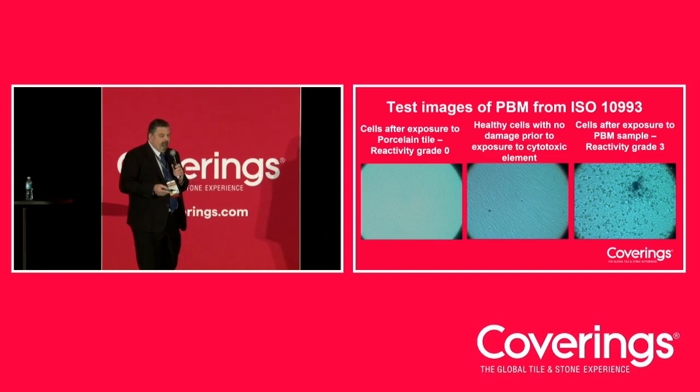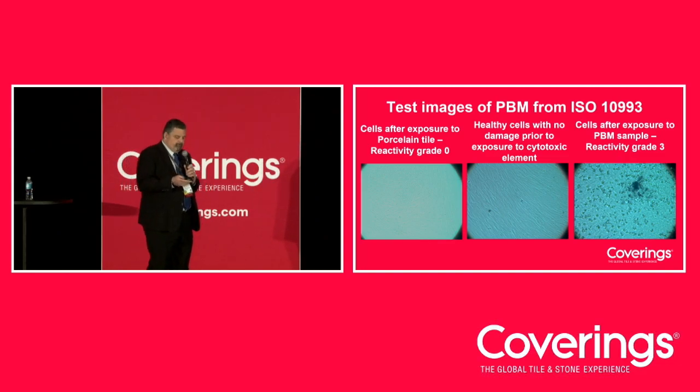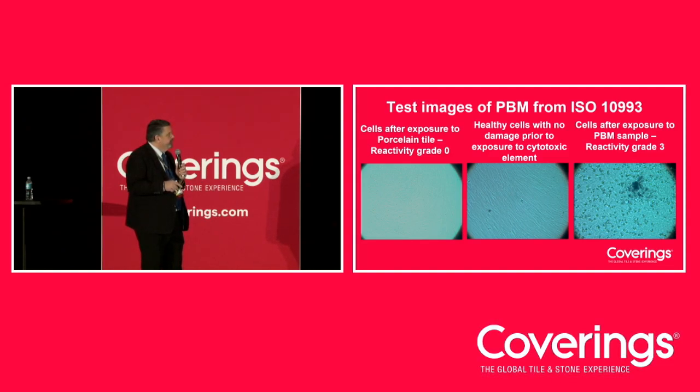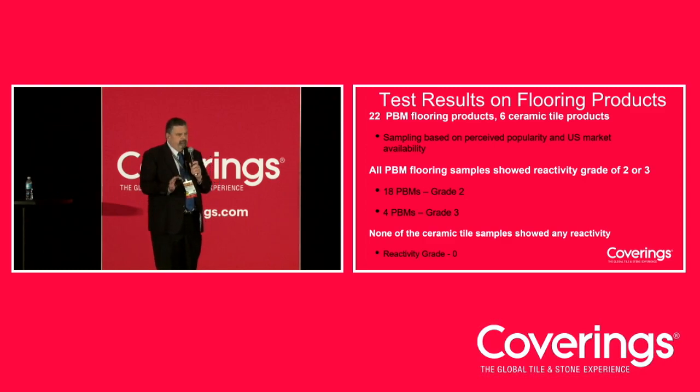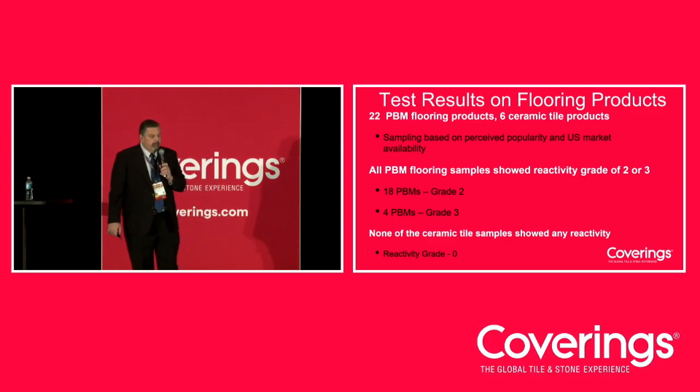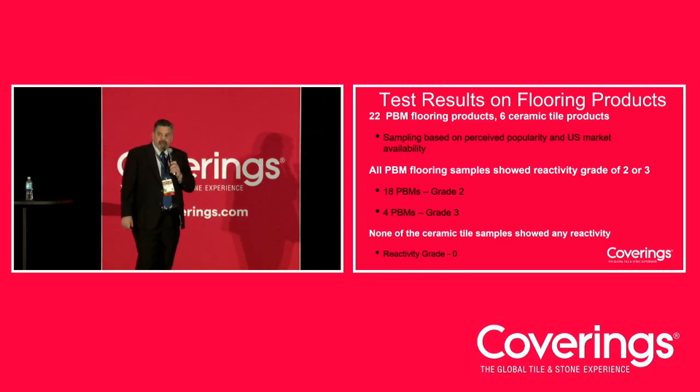So these are some of the actual slides where they did expose the skin cells. This is a tile. You see there's no reaction. This is the before exposure, and then this was after the exposure. And this would have come out at a reactivity of a grade 3. So remember that former slide that shows that table? Grade 3 is a bad actor. People can actually react to these. Of the 22 products that were tested, 18 of them were at least a grade 2. That could be a problem, and 4 of them were grade 3. That is a problem. Of course, all the tile samples, and there were 6 of those, were 0, so there was no reactivity with tile.